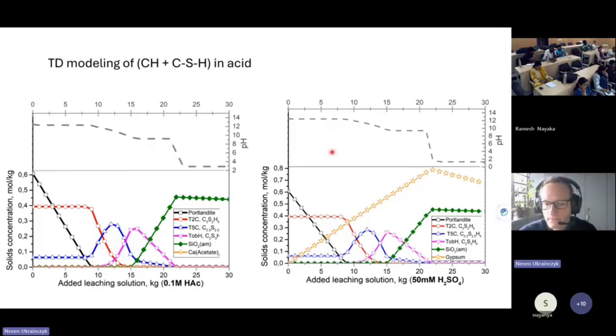So you can predict this, how the portlandite dissolves for acetic acid, and here is for sulfuric acid. When you are adding more and more acid, how the portlandite dissolves, then the CSH is dissolving, and you are precipitating silica gel, and the pH goes down.